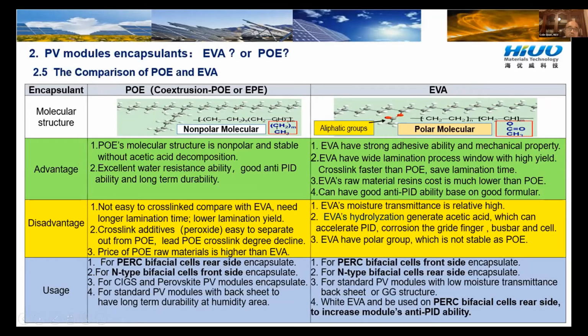So the advantage for POE is that it's very stable without acetic acid decomposition, and it has excellent water resistance, good anti-PID ability, and long-term durability. While its disadvantage is that it's not easy to cross-link compared with EVA, so it needs a longer lamination time, and sometimes there are lamination problems like bubbles, which can lower the lamination yield.